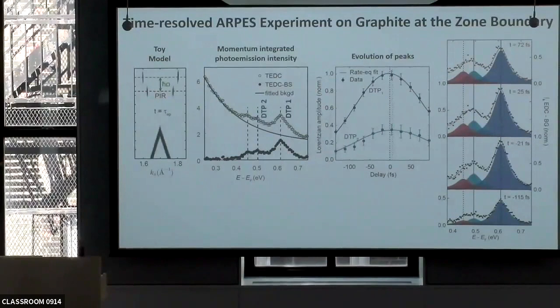The question is then, what does the red structure do? And the red structure also follows that, but with a delay. Delay which is marked here by the red arrow, 42 femtoseconds. And the 42 femtoseconds is interesting not only because you can really resolve a delay, but because that peak has an energy of 165 millielectron volt, which actually matches one of the optical modes for this system.